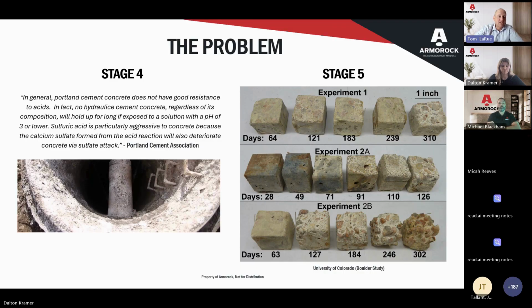The Portland Cement Association states that in general, Portland cement concrete does not have good resistance to acids. In fact, no hydraulic cement concrete, regardless of its composition, will hold up for long if exposed to a solution with a pH of 3 or lower. Sulfuric acid is particularly aggressive to concrete because calcium sulfate from the acid reaction will also deteriorate concrete via sulfate attack.